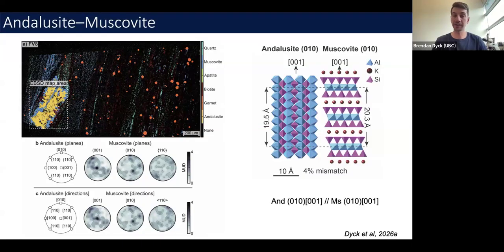Here we've got a single andalusite grain, and it's fringed by this retrograde muscovite. If we take our andalusite, rotate it into our common reference frame, and apply that same rotation to all the neighboring muscovite, what we can see is that the 010 plane of our andalusite aligns very nicely with this maxima in the 010 planes of muscovite.